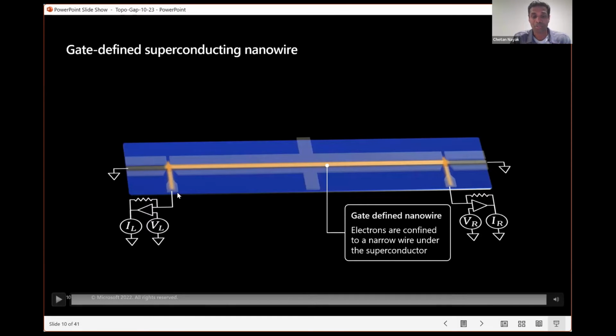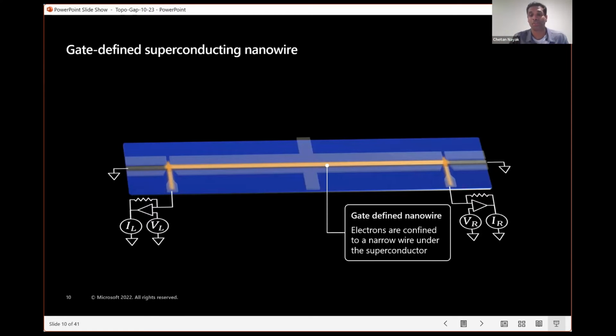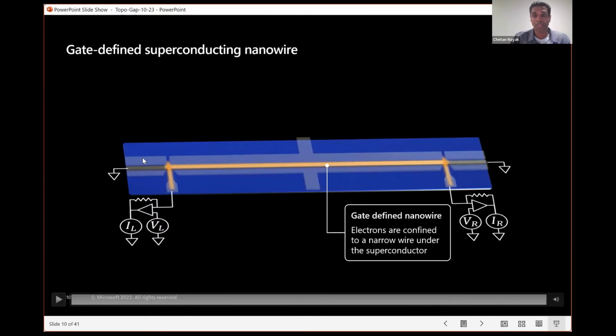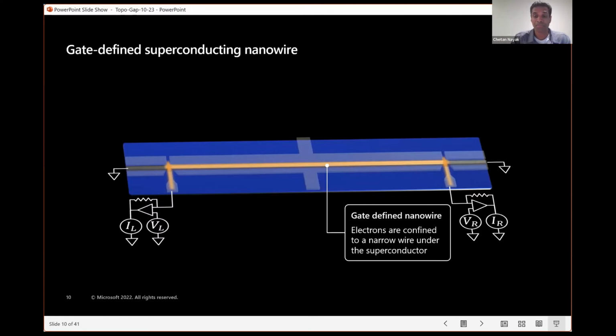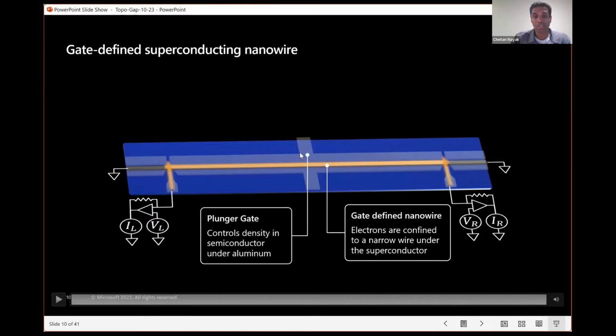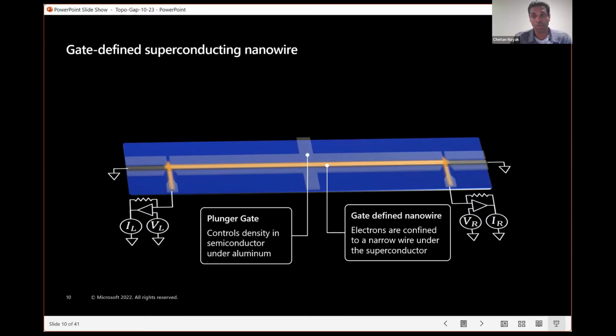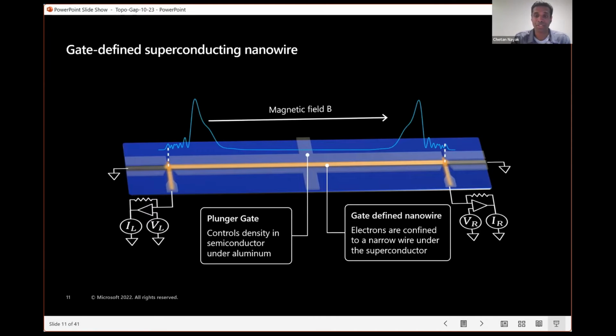Okay. And then there are also some helper gates over here that are at positive voltages that bring some density in from the sides so that we can perform tunneling measurements in which we tunnel some current into the device. Out here, the gates are more negative, so they deplete even underneath the superconductor. And here with the gates, we exercise some freedom to control the density so that it's low and in the lowest subband. We'll see momentarily that it needs to be in the lowest subband, but we can tune the density here with this gate and it doesn't necessarily have to be fully depleted. Okay, so this is how we have a gate-defined nanowire underneath a superconductor. If we tune that density just right and put a magnetic field along the wire, then we will enter the topological phase, and there'll be a local density of states that looks like this, and those are the signatures of Majorana zero modes at the end of the wire.